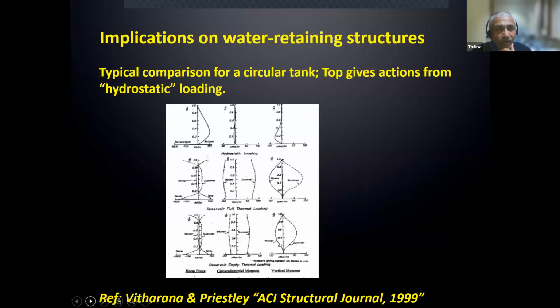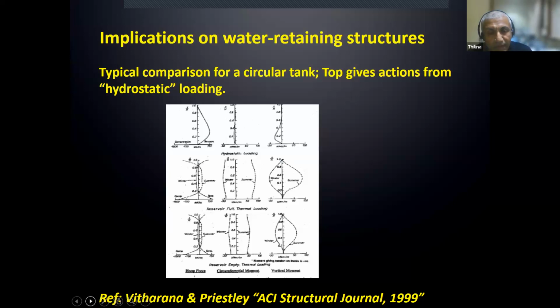So I just put this in as a quick example on the water tank. I published this paper in ACI Structure in 1999. The top one is the hydrostatic loading: bending moment, hoop force, circumferential moment, and the vertical force. The middle one and the bottom are the thermal stresses. It's not time to read the numbers. You can see the difference when it comes to circumferential: 0 on the hydrostatic, but thermal effects dominate. So that's some reason why a lot of tanks in Canada and New Zealand start cracking. That's the reason they look at what is post-cracking, and they find it is the thermal stresses. Again, next one, please.